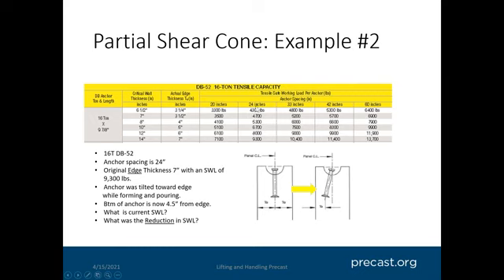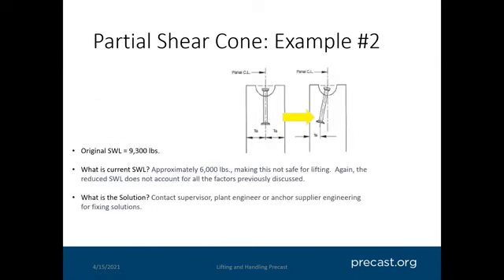The anchor spacing was 24 inches. You have an edge thickness of 7 inches. So you kind of go down the path here. Safe working load is 9,300 pounds. However, it got tilted towards the edge, which created a new edge distance of 4.5 inches. So we come back up here. What's the new safe working load? We went from 9,300 pounds to 6,000 pounds just because of that tilt in the anchor. Again, even though it's 6,000 pounds, the safe working load doesn't account for all the other factors of bending moments and concrete strength, sling angles, and everything else. So again, contact the engineers and figure out what the fixing solution is.